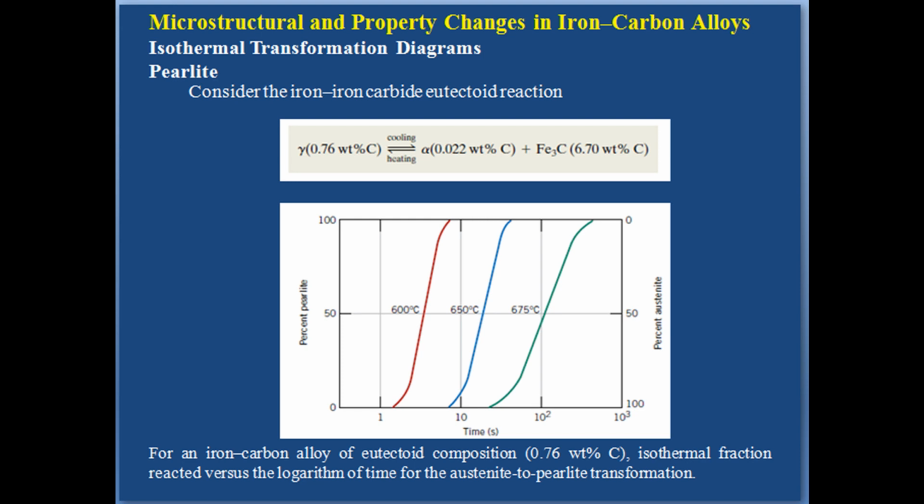The dashed curve corresponds to 50% of transformation completion. These curves were generated from a series of plots of the percentage transformation versus the logarithm of time taken over a range of temperatures. The S-shaped curve for 675° in the upper portion of the figure illustrates how the data transfer is made. In interpreting this diagram, note first that the eutectoid temperature, that is 727°, is indicated by a horizontal line. At temperatures above the eutectoid and for all times only austenite exists, as indicated in the figure.